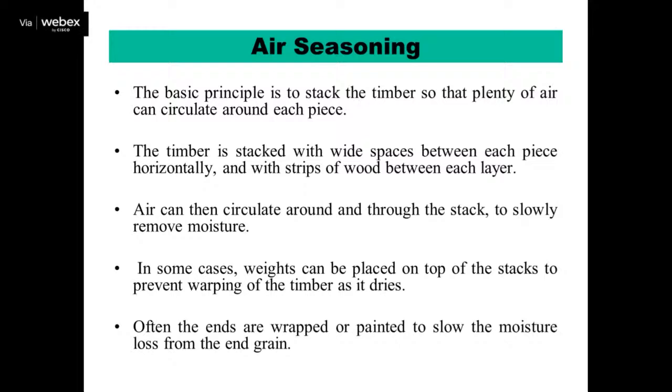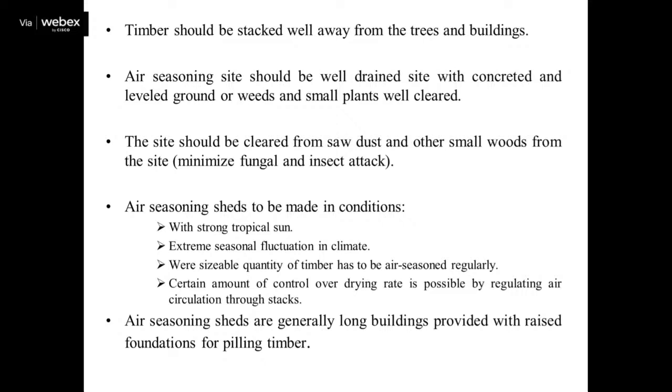In this kind of drying, the basic principles are the same. We have to stack the timber, and once the timbers are stacked properly, the air can be circulated through the stack, which is done naturally. In some cases, we put weight over the top of the stacks to prevent warping, and often the ends are painted for slow removal of moisture from the end grains to prevent end checking. The timber should be stacked well away from trees and buildings. The air seasoning site should be a well drained site, with concrete and level ground, and the weeds and other small plants should be cleared from that site.